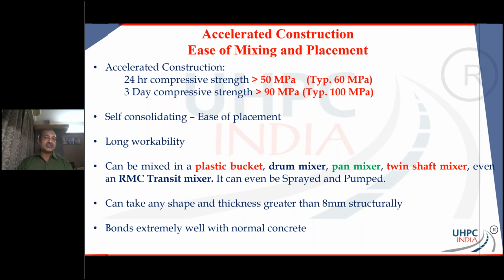One of the other reasons why you should really look at UHPC as something very beneficial, especially in infrastructure markets, is accelerated construction. In 24 hours, it is possible to get a good 60 MPa, 65 MPa strength. And in 3 days, you can be touching that 100 MPa mark. So believe me, if you're doing some repairs on bridges, you can just pour UHPC, and in a couple of days, you're good to open up traffic. That's how good it is.